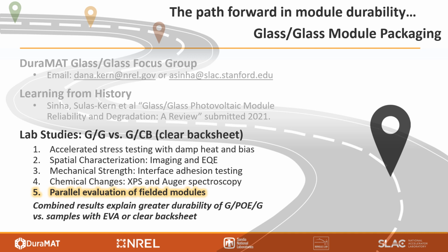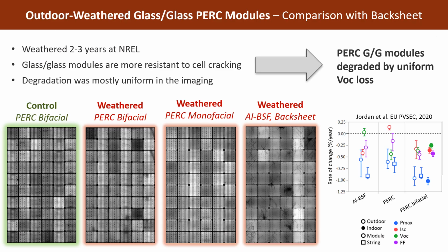Now, before I wrap up, I'll just show you a parallel evaluation of fielded glass-glass modules. This is just a quick example of modules that were weathered outside for about 2 to 3 years at NREL, during which time they were all operating side by side and they all went through a severe hailstorm. The EL images show 3 glass-glass PERC modules starting from the left, which we compare with an aluminum BSF glass backsheet module on the farthest right.